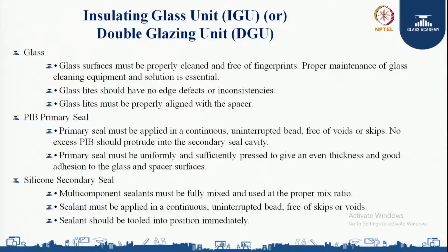Now let us understand PIB, polyisobutylene primary seal. The primary seal must be applied in a continuous, uninterrupted bead, free of voids or skips. No excess PIB should protrude into the secondary seal cavity. The primary seal must be uniformly and sufficiently pressed to give even thickness and good adhesion to the glass and spacer surfaces.